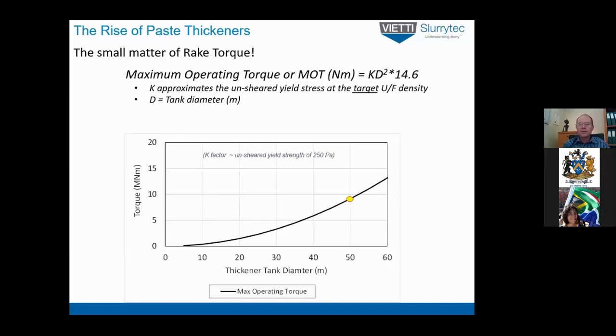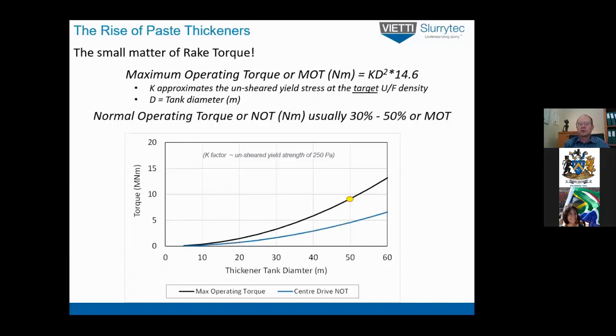Now, when the thickener goes in, the thickener vendors tell the operators, listen, you cannot run the thickener at 100% of rake torque, because your bearings and the gear life of that gearbox will be reduced to a few days. So to keep your gear life for a reasonable length of time, you operate typically at between 25 and say 40% of the MOT. This is called the normal operating torque. So in this particular case, the operators would try to keep the torque down at about 5 million Newton meters, which is way below what the slurry actually requires.